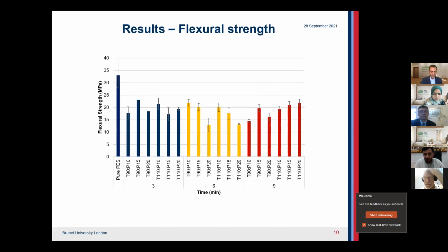Looking at the flexural strength, the processing parameters affected, or the addition of date palm fiber affected the development of the composite negatively by reducing its strength, which might be due to the hydrophilic nature of the composite, along with no chemical treatment used for the fibers, no additives used. So there is a lack in the interfacial bonding between the fiber and the polymeric matrix,